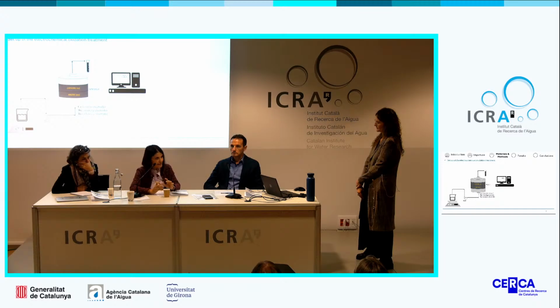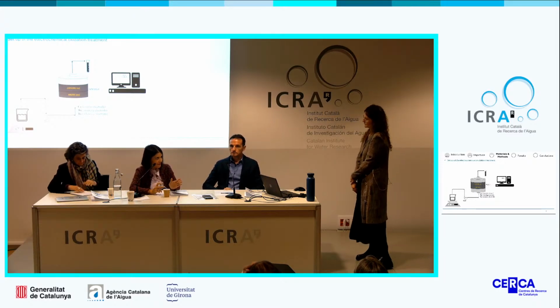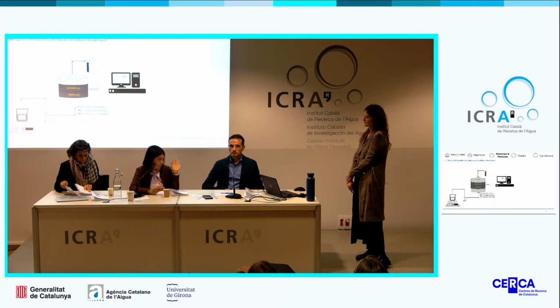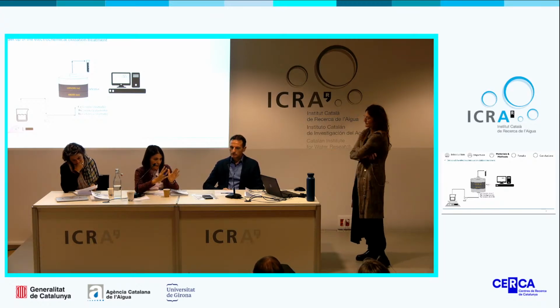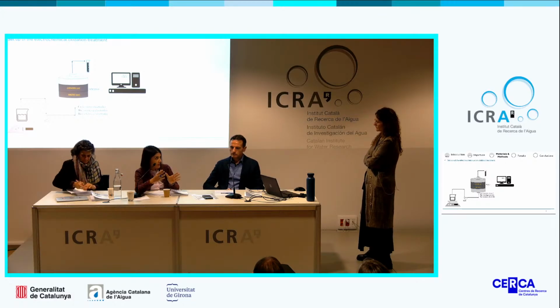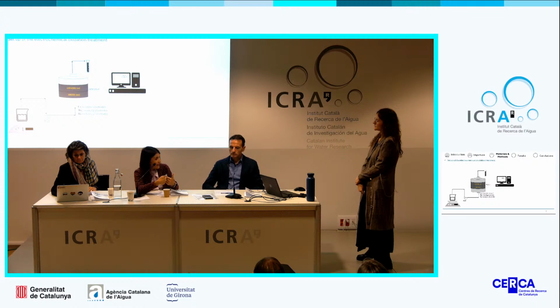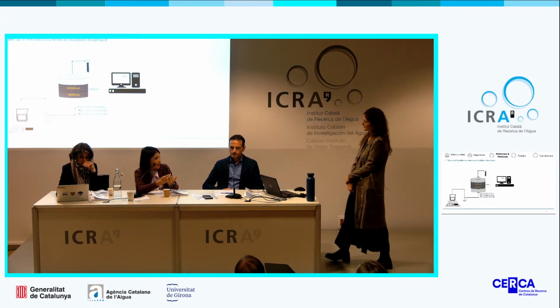Well, regarding absorption, the absorption is a very key point in your process, no? I'm right. You evaluate the absorption capacity of your material, and you extract with methanol the amount of antibiotics retained in your material. But after the treatment, you evaluate again the amount of organics retained in your electrodes. The nature of these organics is the same. I didn't get the question.